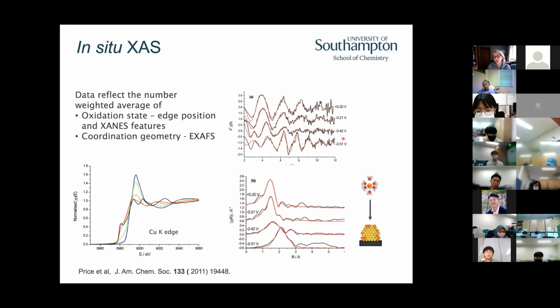To interpret X-ray absorption spectra, the EXAFS part, we take the Fourier transform. And so here are the Fourier transforms of those, and the red lines are the fits. So you can see we start off with some neighbors that are between 1 and 2 angstroms, and we gradually move to having the coordination environment change so that the neighbors are at longer distances. Now these are not phase corrected, so you can't just read the distances off the plot, right? You need to fit the data. But again, it's showing us that we're going from these hydrated copper ions to copper sitting on the gold. So that's the perspective of the copper ions.